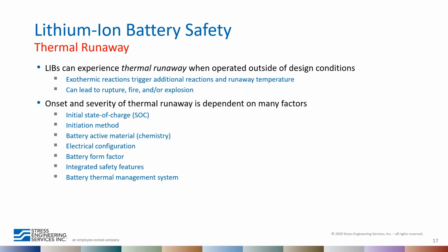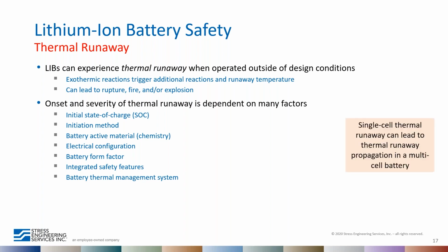The method used to initiate thermal runaway, whether it's external short or external heating, the active material used, the chemistry in the cathode in particular, the electrical configuration, the form factor, integrated safety features, and the method used for thermal management. Those are all very important. And something that's going to be a key theme in the presentation moving forward is that single cell thermal runaway, while it's a problem, the worst scenario is when that single cell emits a lot of heat and causes a propagation of thermal runaway in a multi-cell battery.